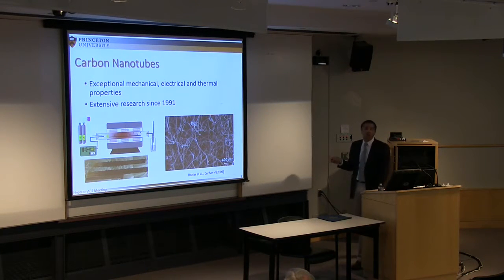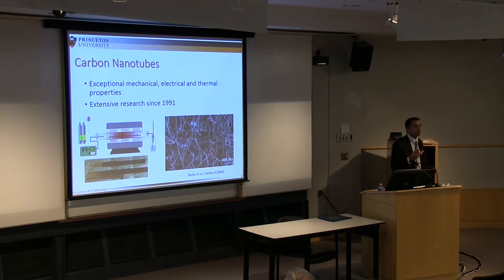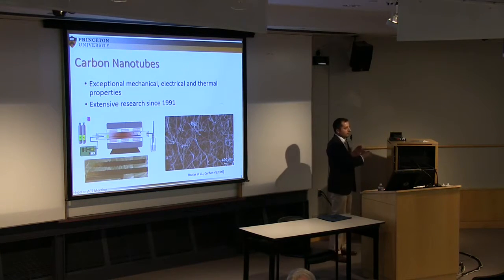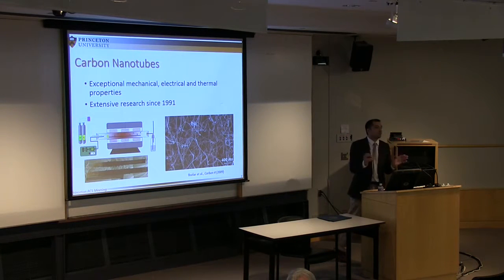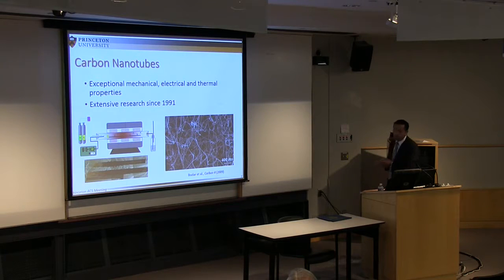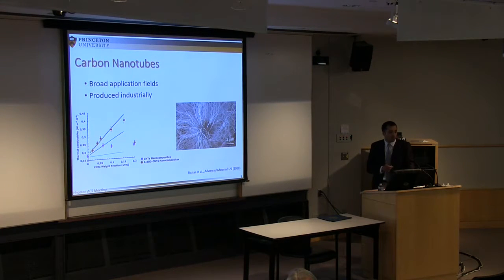Unfortunately, this configuration makes it difficult for ultimate use. Whereas in the case of carbon fibers, the way they are synthesized from polyacrylonitrile is very well controlled, so you have perfectly aligned fibers that come as a textile. So aligning the carbon nanotubes and dispersing them, because they tend to aggregate due to van der Waals forces, is a big problem that we also have with graphene. Not really alignment, but more the aggregation.